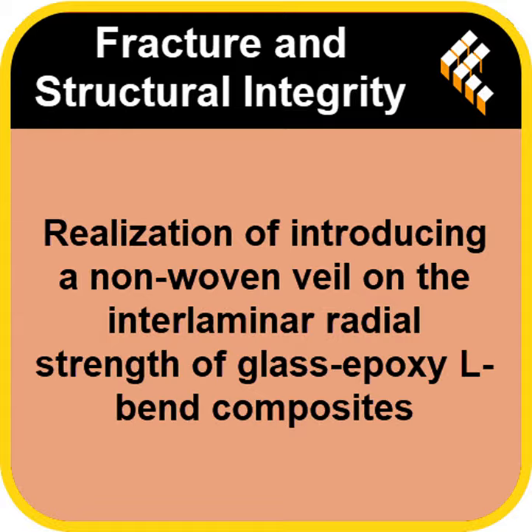Now contrast that with the champion, the 15 g/m² carbon veil sample. What did that one look like after breaking? Totally different story. You saw clear signs of matrix deformation. The epoxy itself had stretched and flowed before it fractured, meaning it absorbed energy. Not just a clean break. Not at all. You also saw features called river lines on the matrix surface, which again indicate the crack had to fight its way through, dissipating energy.